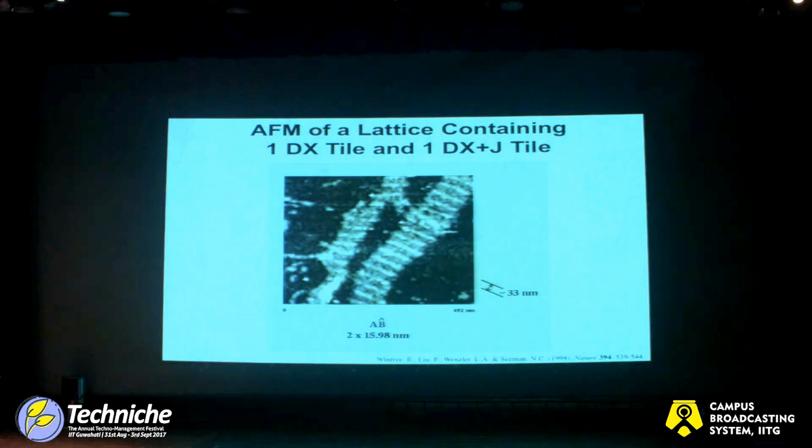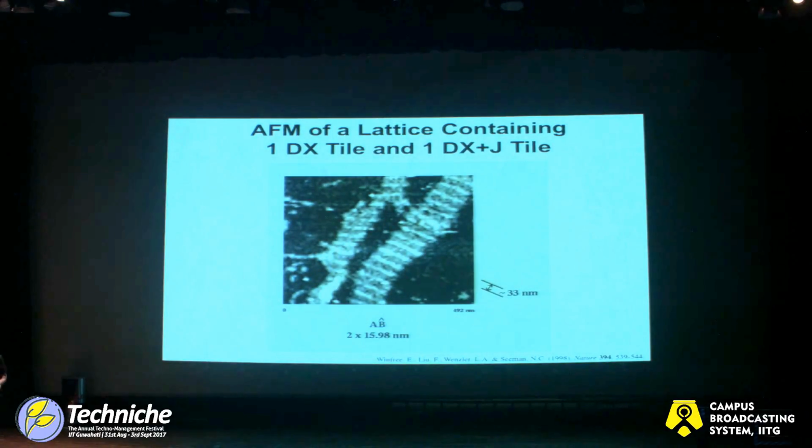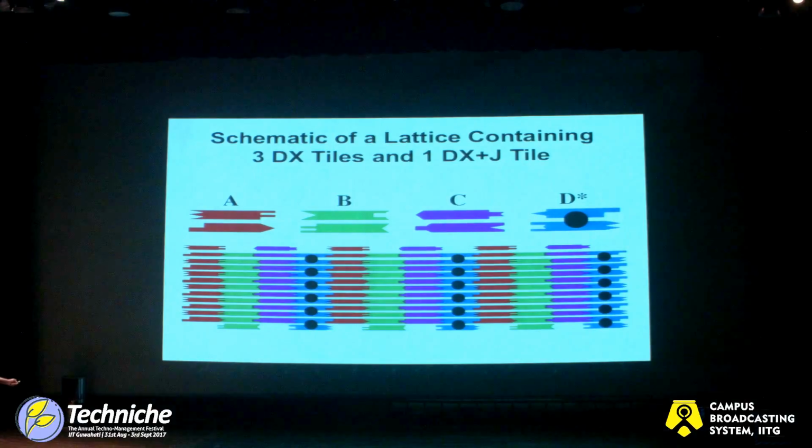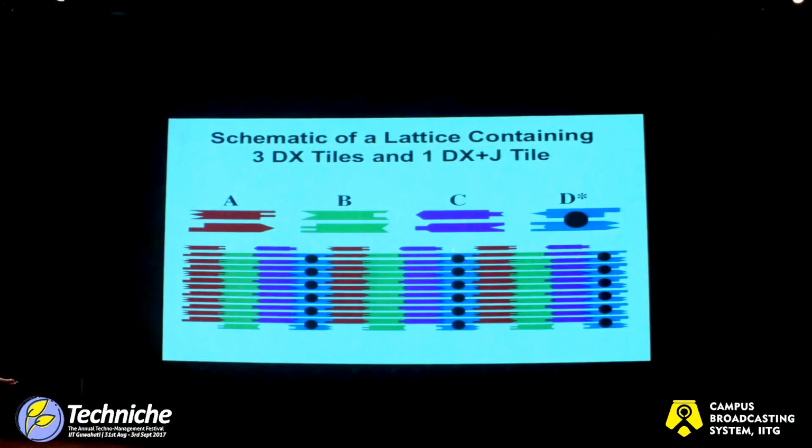Now, there's a basic rule of microscopy. It doesn't matter whether you're using a dissecting scope, an electron microscope, an atomic force microscope like this, or what have you. If you go looking for something, you're going to find it. So you have to run controls. So the control that we ran is shown over here, where we took 4 molecules like this and stacked them together. And now we should have those stripes separated by double the distance, about 64 nanometers.